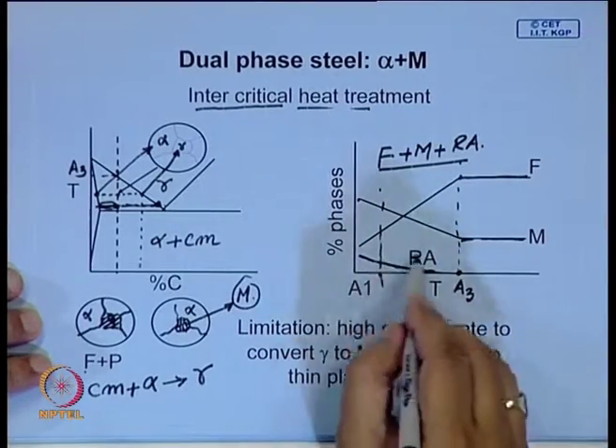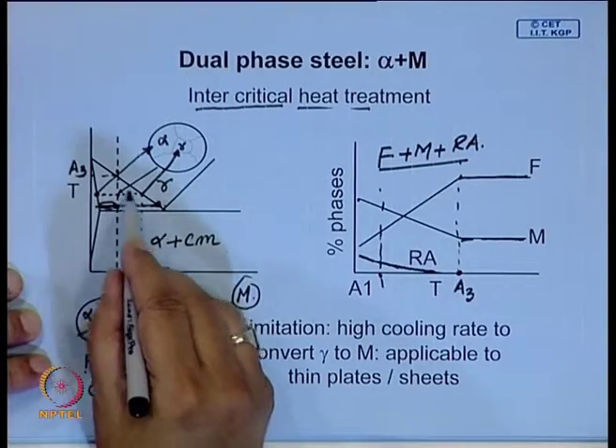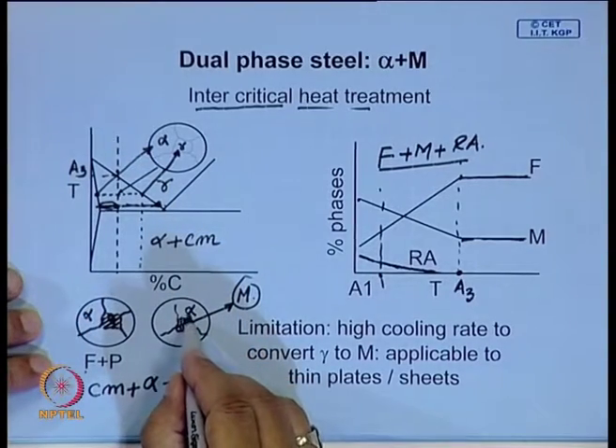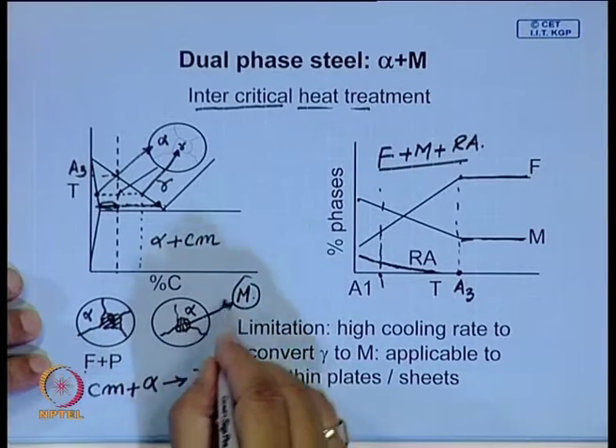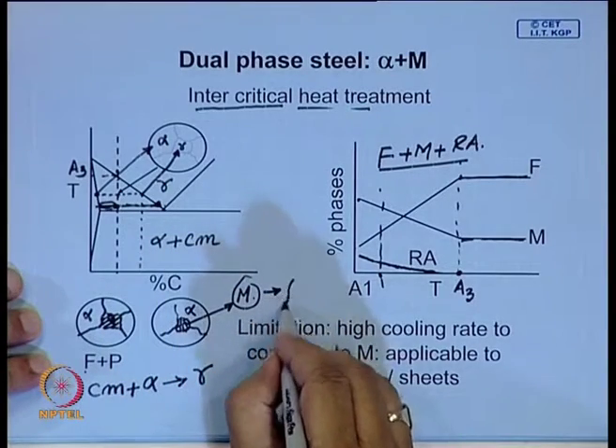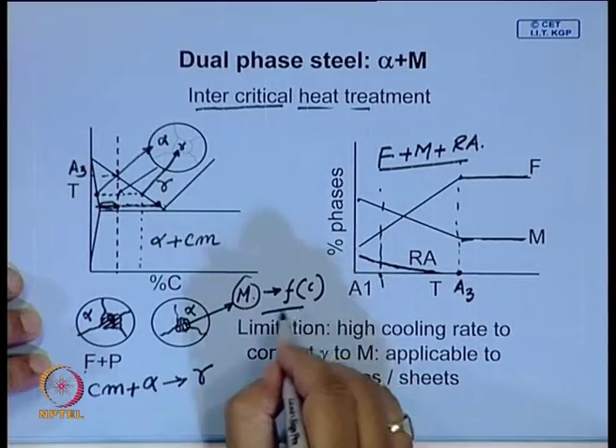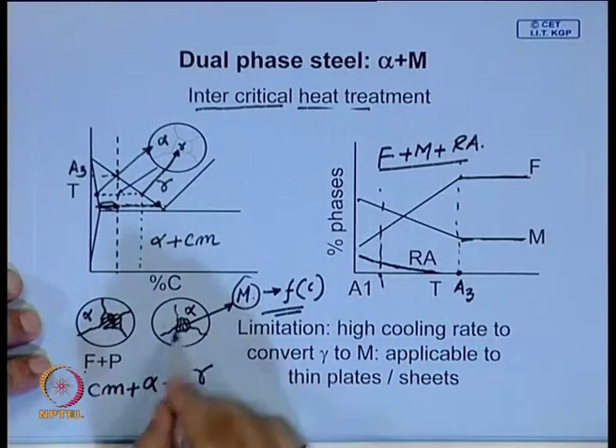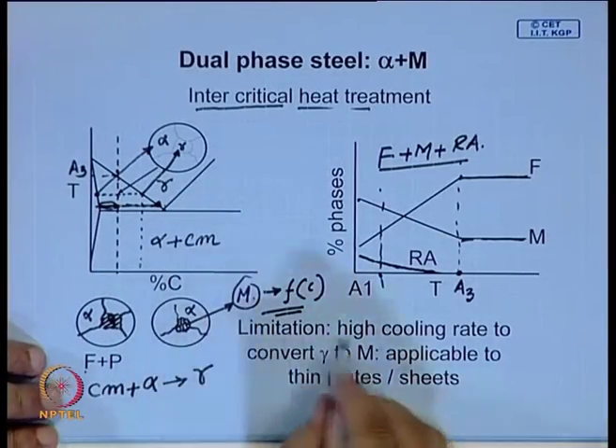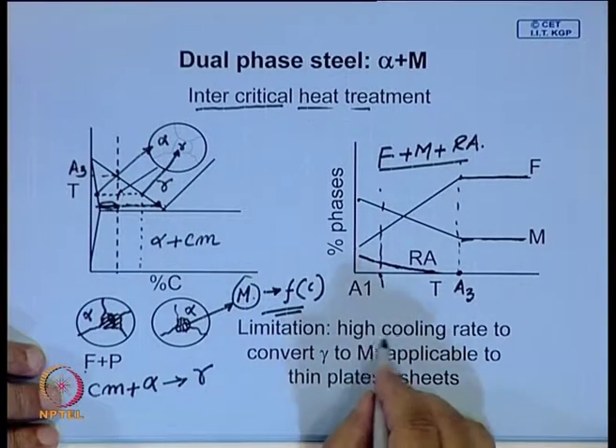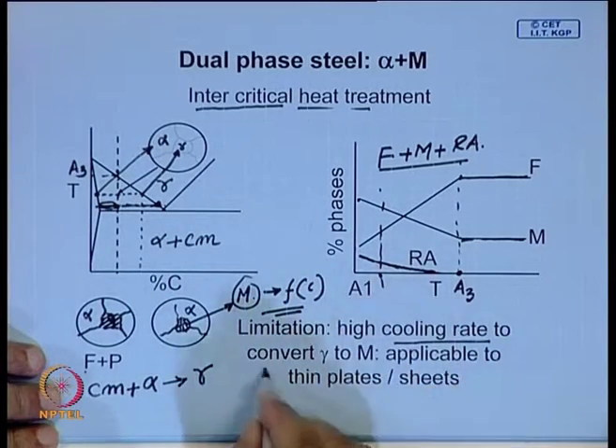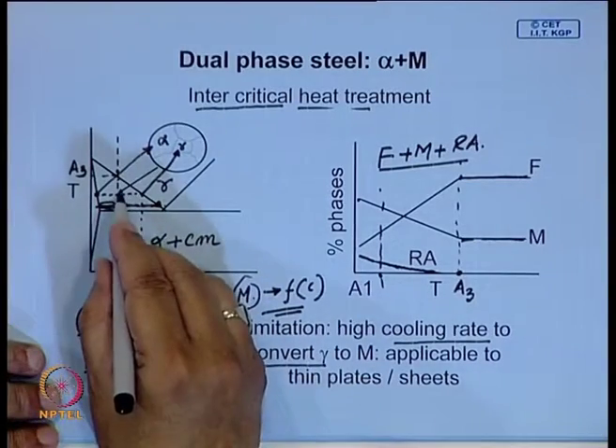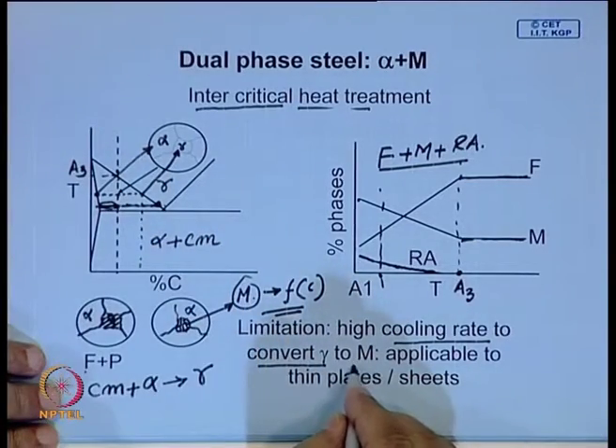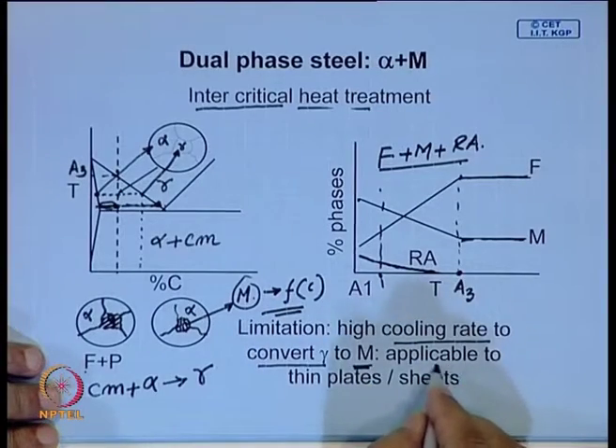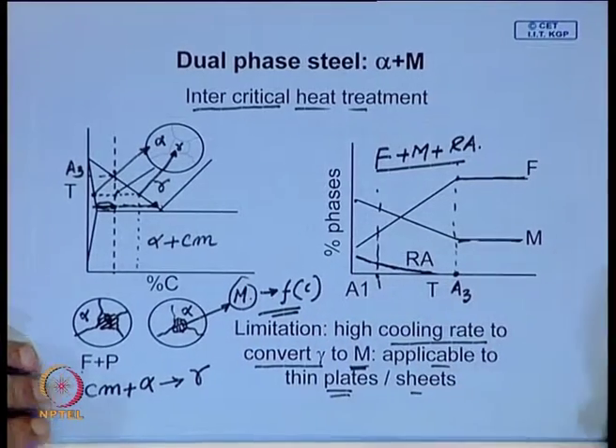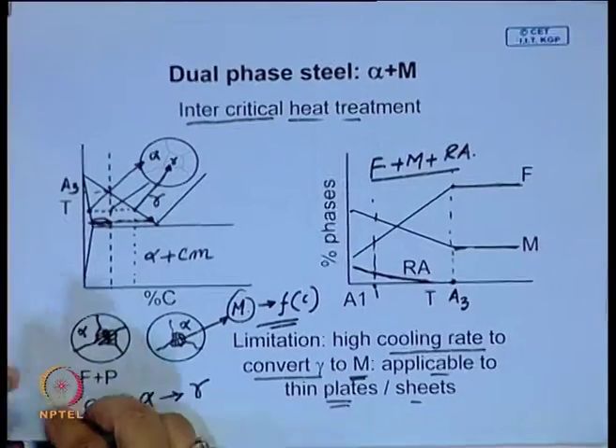But the advantage of having a duplex structure somewhere in between is that there is a possibility you will get a stronger martensite, because we know the strength of martensite is a function of carbon content. So, it is likely to have much higher strength, but the limitation of this dual phase steel is that a high cooling rate has to be adopted to convert that austenite to martensite in plain carbon steel, and it is applicable to thin plates and sheet. So, the size limitation stays.